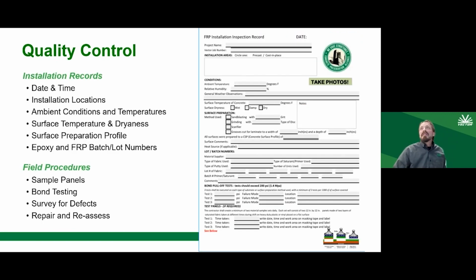So quality control, this is a typical sheet. We want to know what's the ambient temperature. We don't want to install this when it's blazing hot or if it's incredibly cold. Epoxies don't like hot temperatures, and they don't like cold temperatures. So we want to make sure that our ambient temperature, whether it's inside of a containment or inside of a building or whatever, is correct and not too hot, not too cold, and that steps are being taken to ensure that the layup environment is conducive for the installation of FRP.